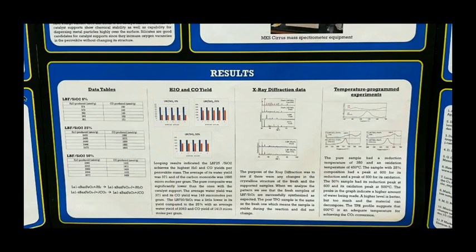Lastly, X-ray diffraction was used to evaluate the material stability, as changes in the crystalline structure would indicate low material stability and poor long-term endurance. By looking at the graph, we can observe that the structure of the material did not change after the TPO experimentation. The main peak in the graph shows the material can maintain its structure. The post-TPO graph shows the same peak as the fresh sample, which shows that the material did not crumple and decompose even after the heating, which means that the silica did help to support the perovskite structure.